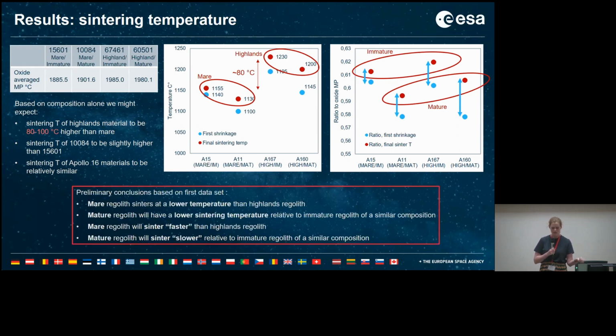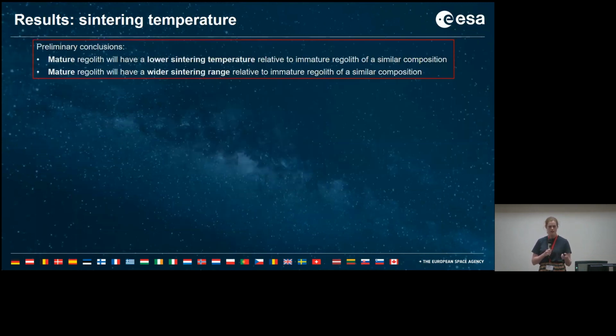So some preliminary conclusions based on the first data set: that Mare regolith sinters at a lower temperature than Highlands regolith. Mature regolith will have a lower sintering temperature relative to immature regolith of a similar composition. Mare regolith will sinter faster than Highlands regolith, and mature regolith will sinter slower relative to immature regolith of a similar composition.